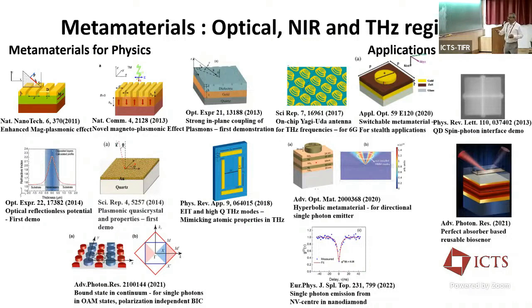So this is something which is similar to the first talk in this afternoon session. Like EIT, we have 2 quadrupolar resonances induced by the dipoles at the top and the bottom. These 2 quadrupole modes interact, and we showed that we can control the final resonance, and we could show highest Q factors at terahertz frequencies. So that's one thing. From the application point of view, I'll show some applications. This is a stealth application.